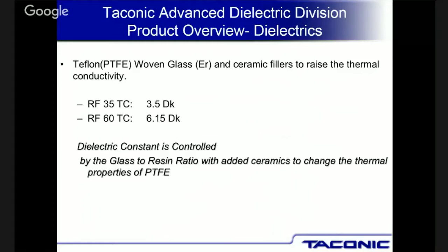And then we also developed the RF 60 TC, which is 6.15 Dk, which is pretty nice material as far as thermal conductivity, and we raised that from a 0.3 to a little over 1. It's again nowhere near what copper is, but it's a very, very good low loss material and good for shrinking. So he could get some advantages on going to the RF60 TC to get the pallet smaller. It's a requirement now, George.